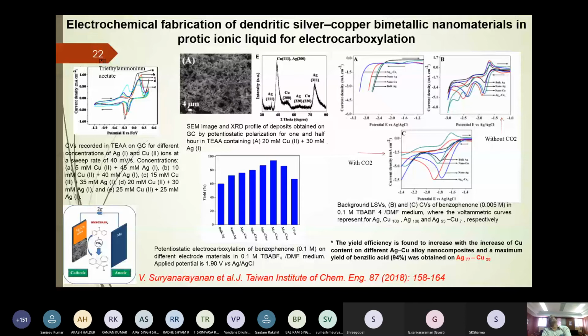The next slide shows CV of many compositions of silver copper, as well as pure silver nanoparticles and pure copper nanoparticles. There, Ag93 Cu7 shows a lower potential compared to others. This shows that it behaves as a good catalyst. The bottom panel shows the yield of benzilic acid for many compositions of silver copper alloy plus pure silver and pure copper. For example, silver 77, copper 23 shows the highest yield. This shows that this particular alloy gives the highest yield of the compound.